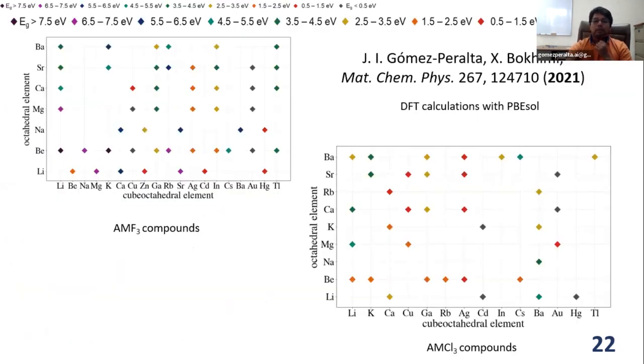Well, as I told you, the purpose behind making these classifiers was to find candidate compounds to adopt the perovskite structure. And in this work, we used an artificial neural network to assess the probability of a proposed compound to adopt the perovskite structure. The one with the results I'm showing you now was trained with compounds with up to 4 Wyckoff sites and was trained to only distinguish compounds having the perovskite structure and those that do not have this kind of structure.